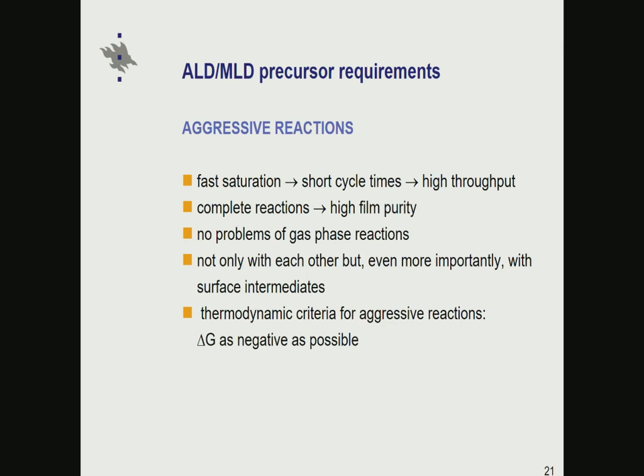And as said already, it is very important that the reactivity is high also towards the surface intermediates left by the other precursor. Thermodynamically, this means that one is looking for reactions that have as negative a Gibbs energy change as possible. Sometimes, especially when using inorganic precursors, we have thermodynamic data available and can easily calculate these Gibbs energy changes. Unfortunately, when making new precursor molecules, we don't have the data available, and then we can't use this criterion.